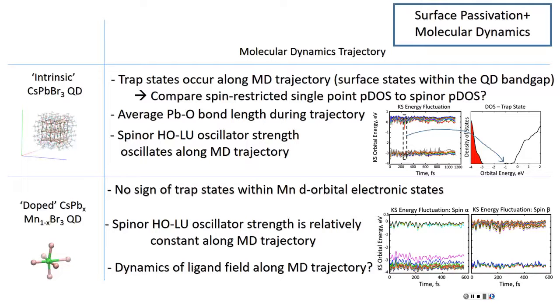I think with this one it would be much easier to understand, at least at 0 Kelvin. But to be more accurate and specify your initial conditions, you can take your spectra at room temperature, average over your ensemble, and hopefully still resolve the 3 peaks, but they will be broader and probably shifted to red more compared to your 0 Kelvin calculations. Looking at this one, the orbitals usually go down in energy rather than up. So on average, you probably will have smaller gaps than at 0 Kelvin.